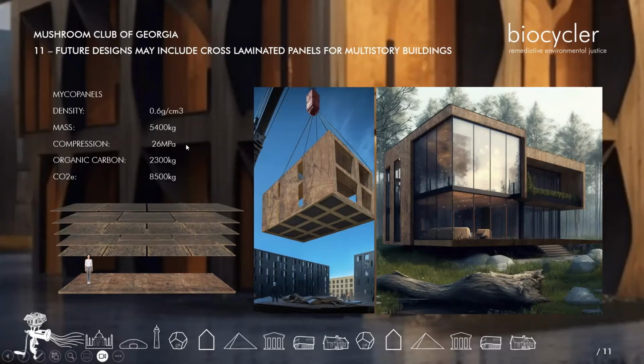Well, we know a way to break down lignin, right? Everyone in this room knows the white rot fungi basically can break down that lignin. So by having that breakdown of that material makes the cellulose more easily align, which makes the compacted material much, much stronger and makes it more durable in the long run.